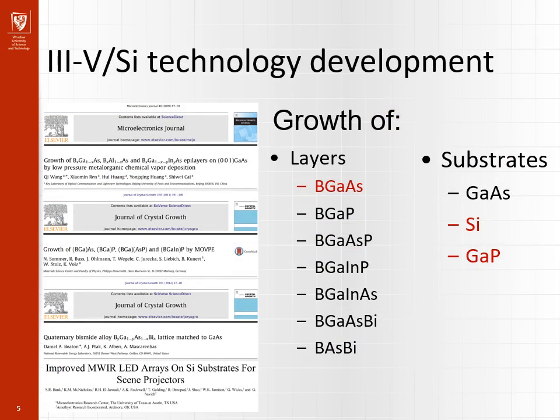Recent advances in growth technology allow the production of new materials containing boron. From this set of materials, boron-gallium arsenide is especially interesting because growth techniques of gallium arsenide are very well developed. Gallium arsenide is a well-known material from applications in light-emitting devices. Boron-gallium arsenide is a ternary alloy, so the simplest possible kind of alloy within 3-5 semiconductors, and it allows us to produce material characterized by a lattice parameter equal to the lattice parameter of silicon.